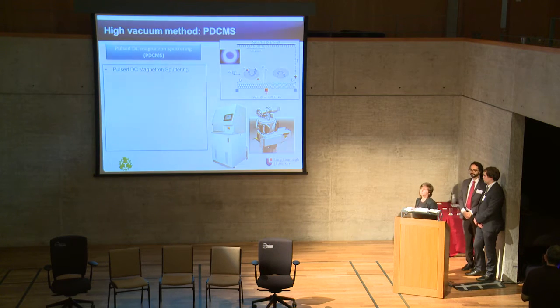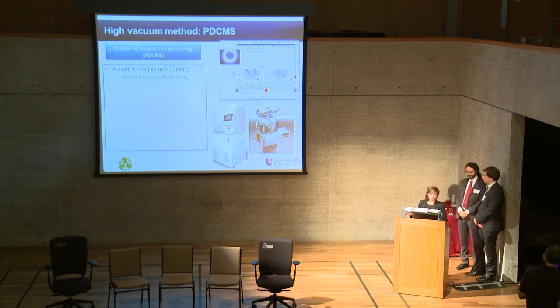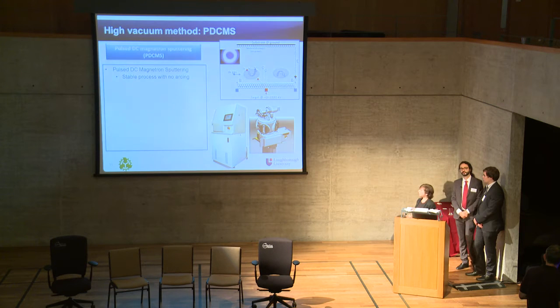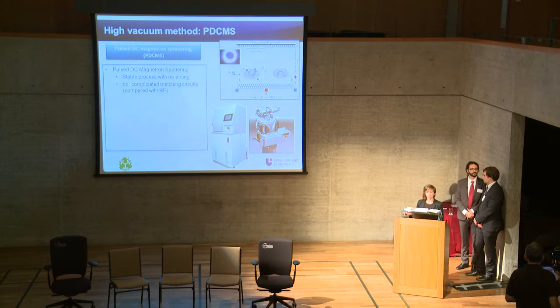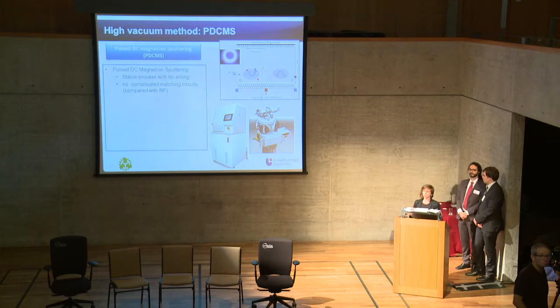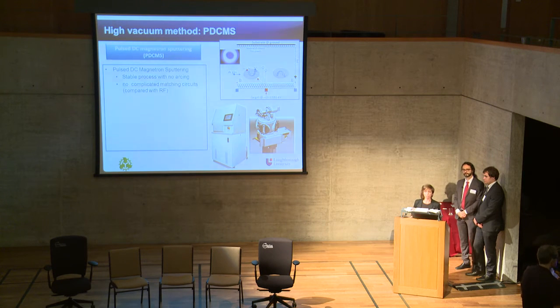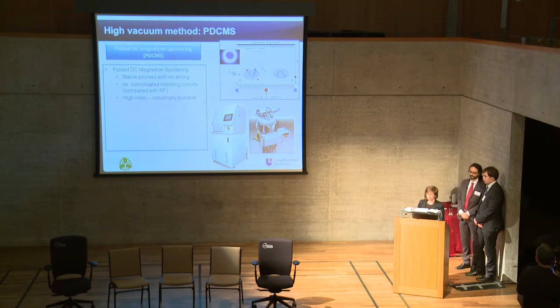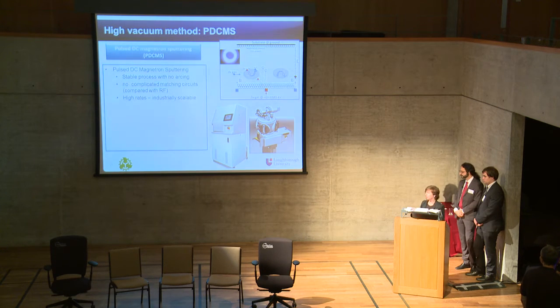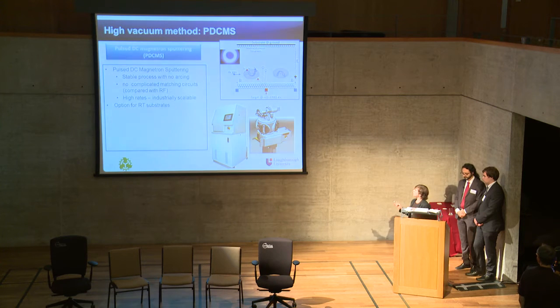That's why we decided to use a novel process, in particular a novel application for photovoltaics. It's a high vacuum method called pulse DC magnetron sputtering. Why? It's a stable process without arcing. It doesn't need complicated matching circuits, which are needed instead for the conventional RF sputtering. We can achieve high deposition rates, so that's why it's an industrially scalable process. There's the option for working at room temperature.